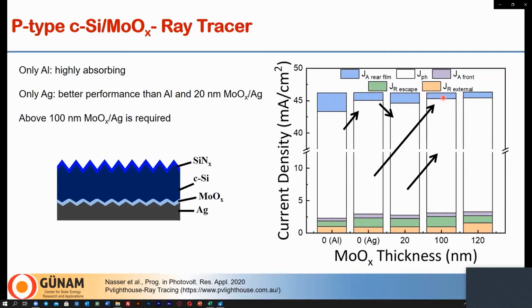So 100 nanometer or more is required now. This is because a dielectric layer with enough thickness, of course weighted with refractive index, is essential to fully block the excitation of surface plasmon polaritons at the back surface. So with a thick dielectric, you can eliminate the parasitic plasmonic infrared light absorption by the rear metal.